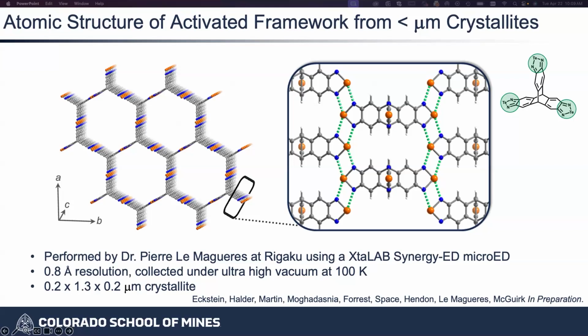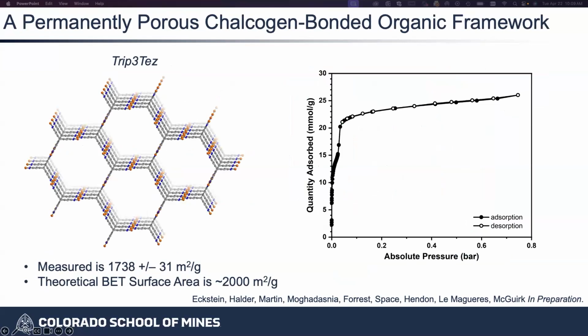And what was super important here is that these are collected under ultra high vac. This structure is stable under ultra high vac, which tells us that it's permanently porous. And so here's that gas adsorption isotherm, 77 K nitrogen, that clearly shows that this system is permanently porous. And so by using the microED, we are able to then correlate that structure to our permanent porosity.